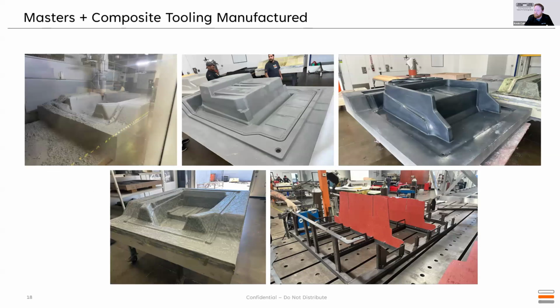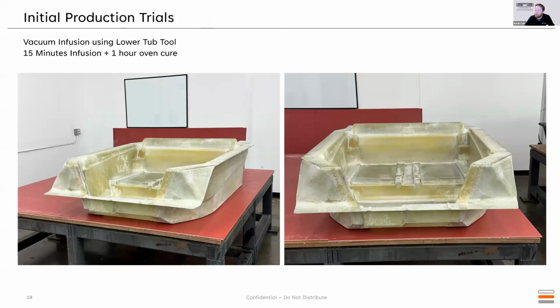These are some photos demonstrating our tooling process internally, machining the masters, polishing the masters, prepping them, to doing the composite molds, reinforcing the molds, and that got us to our very first trial with the full-size tub. And again, it's around a 15-minute infusion, and using this resin system, it requires about an hour cure, but we'll be looking at production systems which have enabled a snap cure process.